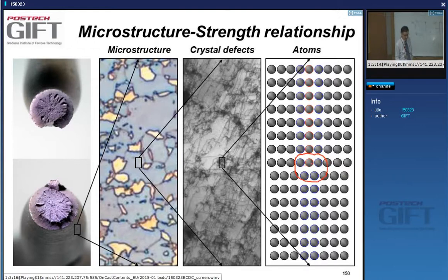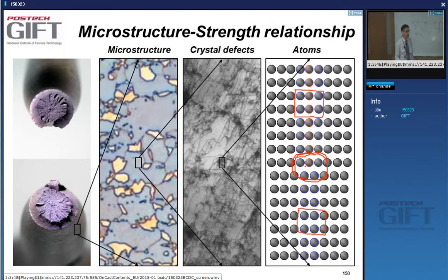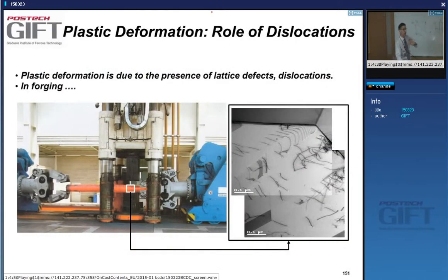To summarize strengthening in steels: we want high density of tiny precipitates, small grain sizes, possibly deformation to strengthen via strain hardening, and additions of phosphorus, silicon, or manganese for solid solution strengthening. Certain of these are related to alloying, deformation, or processing — very often a combination of all three. We'll talk about this in more detail on Thursday.